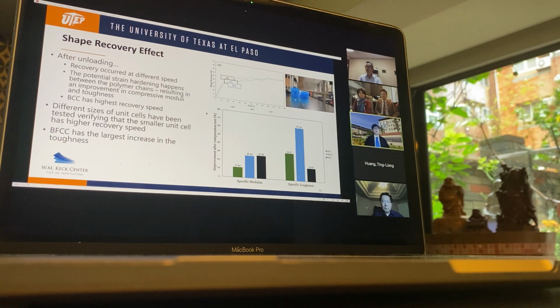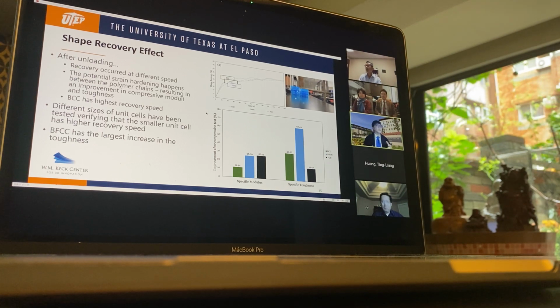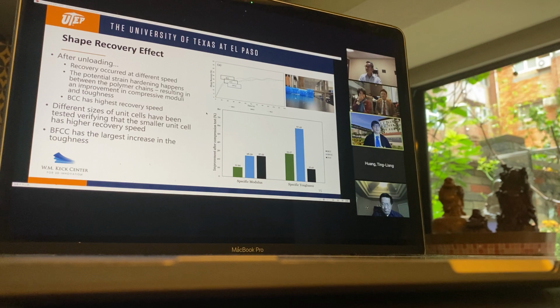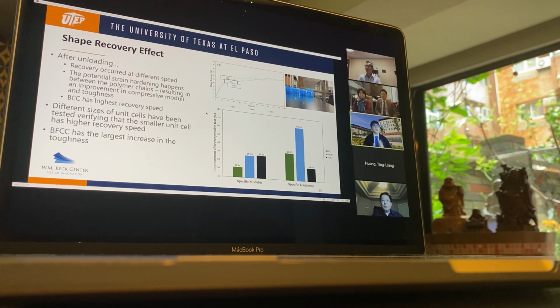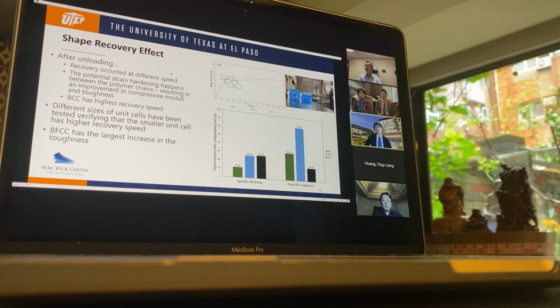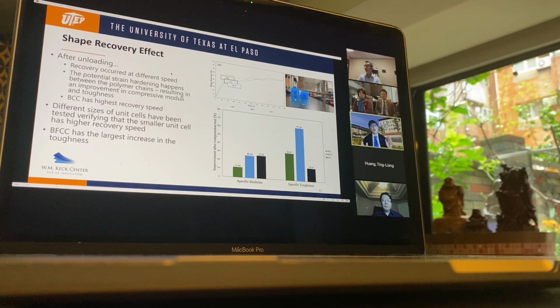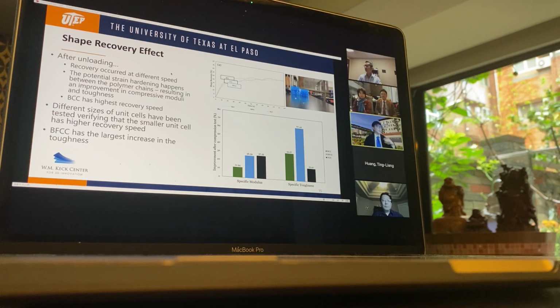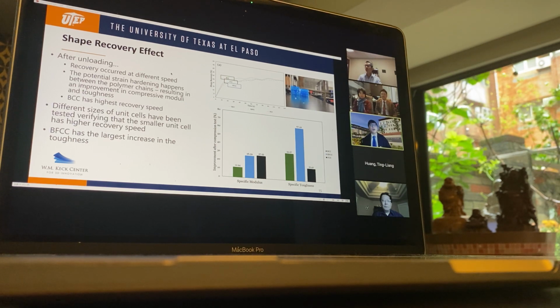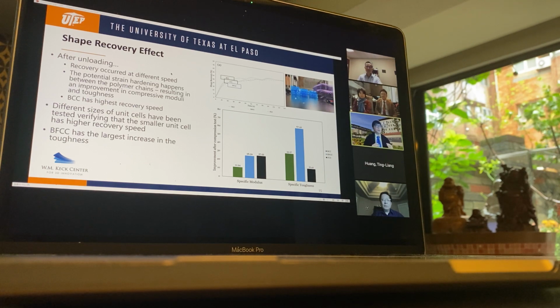So after unloading, it's theorized that the shape recovery occurs because of the strain hardening mechanism in the polymer. So it is the strain hardening mechanism that increases the Young's modulus and the toughness. And we visualize the shape recovery ratio versus time in this diagram. So here, you can notice that the fastest shape recovery happens in the BCC structure, then FCC and BFCC cube.